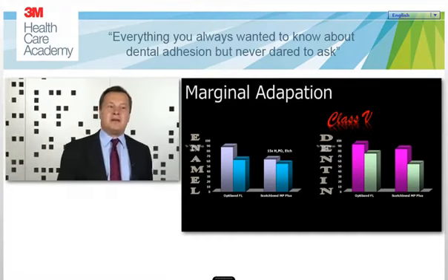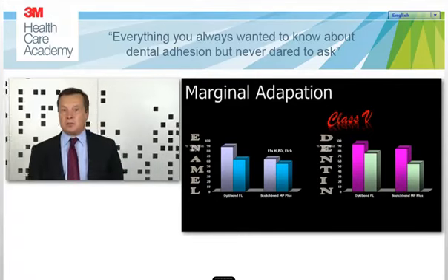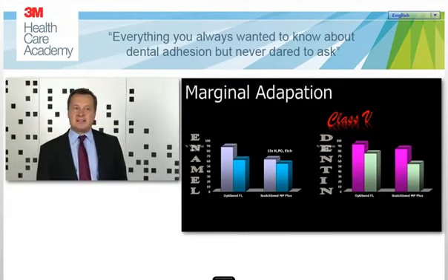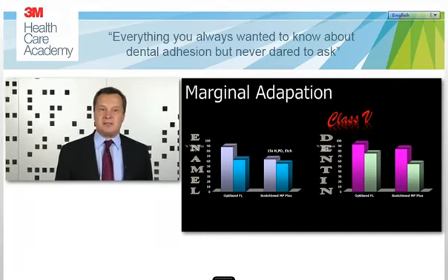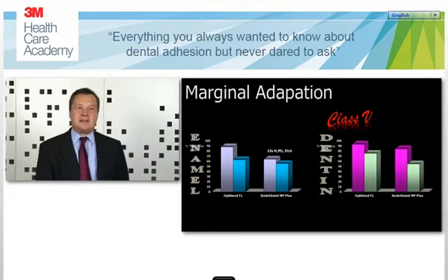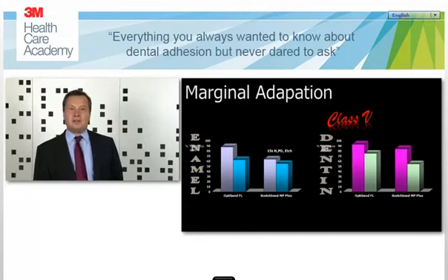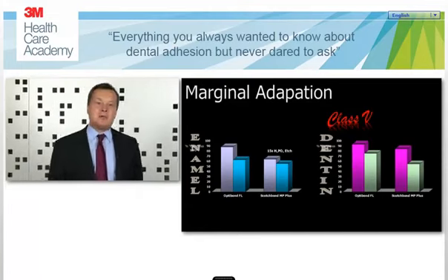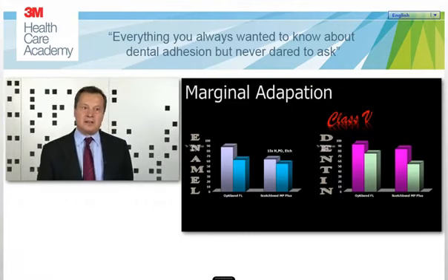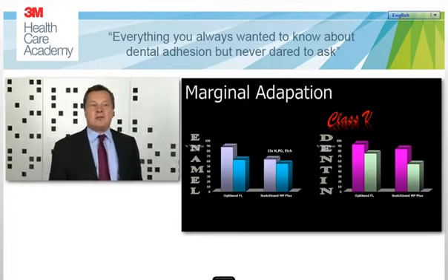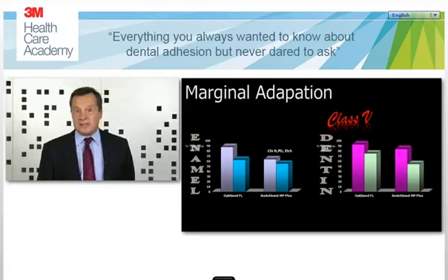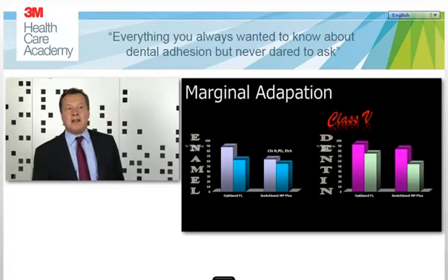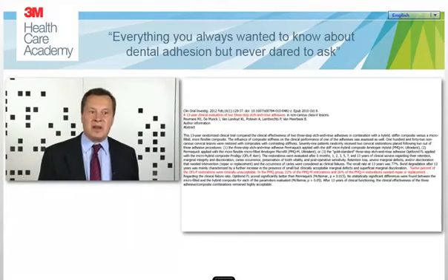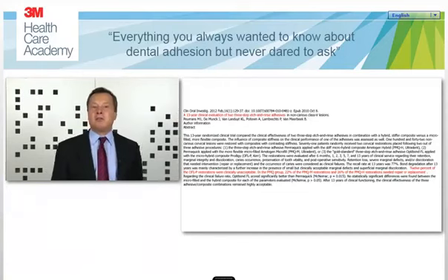What is quite interesting, if you compare with our methodology, for example, Optibond FL with Scotchbond Multipurpose Plus, another etch and rinse classic three-step adhesive system, you will see that there are differences, meaning that a class of an adhesive system does not necessarily mean or define the behavior. You may have different results with the same type of adhesive systems, but with two different types of products. But coming back to Optibond FL, at the end, you can consider this type of marginal adaptation as the gold standard in our test, because Optibond FL has a very nice 13-year clinical study, which has been done by the group of Bart Van Meerbeek, where he proved that this material, even on the long term, behaves very, very well. So it can be really considered the gold standard.